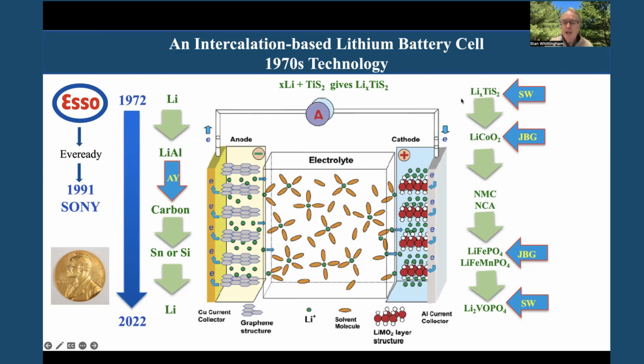On the cathode side, we start out with this layered compound, titanium disulfide. I show you this is the structure here. This works very well. It's a metallic conductor. So that in an electrochemical reaction, you've got to move electrons in and out, as well as lithium ions in and out. So this worked exceptionally well. The voltage, however, was only about 2.5 volts.